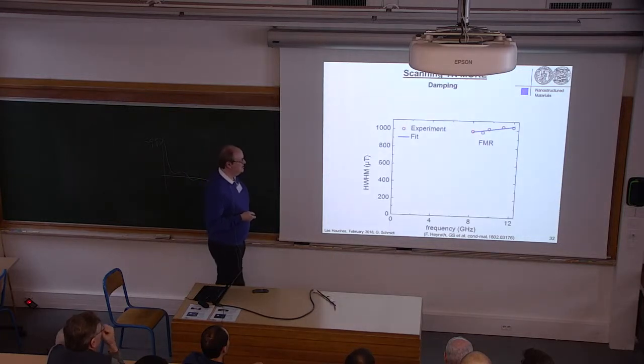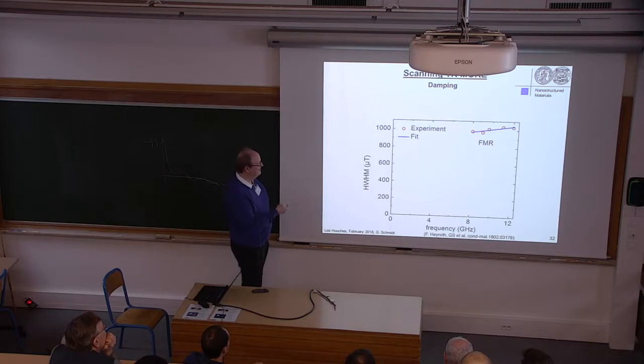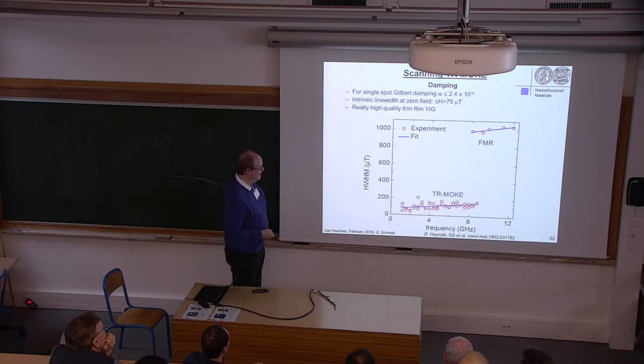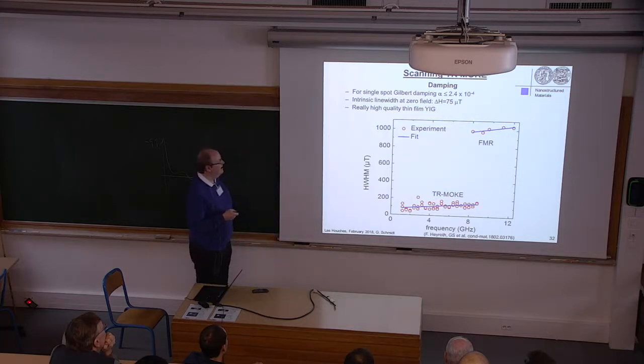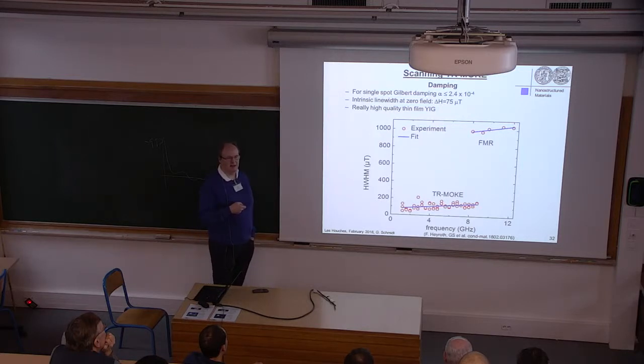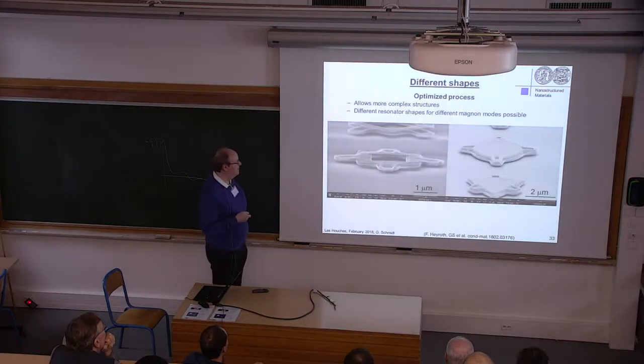And we have also measured the damping, and this is why the diagram was so large in the beginning. So here are the values from the TR-MOKE. You have the line which is very narrow, and the intrinsic line width at 0 field is 75 microtesla, that means 0.75 Oersted, and the damping is 2.4 times 10 to the minus 4. So this is really high quality stuff.